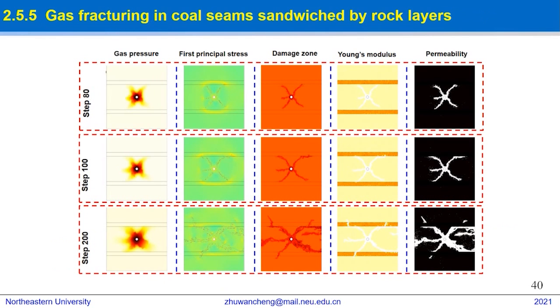From the simulation results, we can see that the rock layer has an obvious barrier effect on fracturing pressure wedging. When the crack encounters the rock layer, the principal stress forms a stress concentration on the contact surface between the coal seam and the rock layer. From the damage zone, when the damage extends to the rock layer, it will pass through the rock layer and continue to propagate, and the whole fracturing process of gas fracturing is mainly induced by tensile damage. The permeability distribution shows that the interface between coal seam and rock layer will form an area with increased permeability.